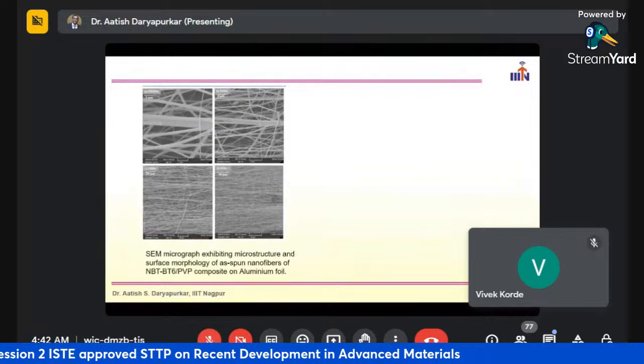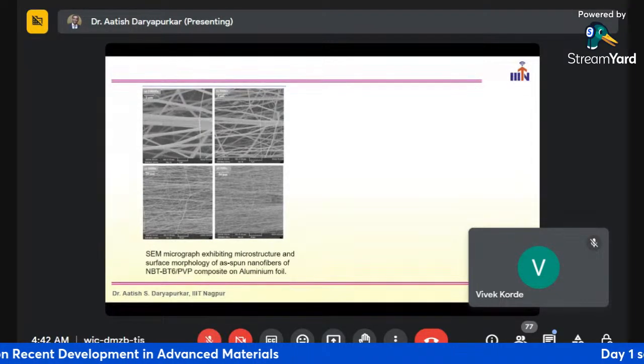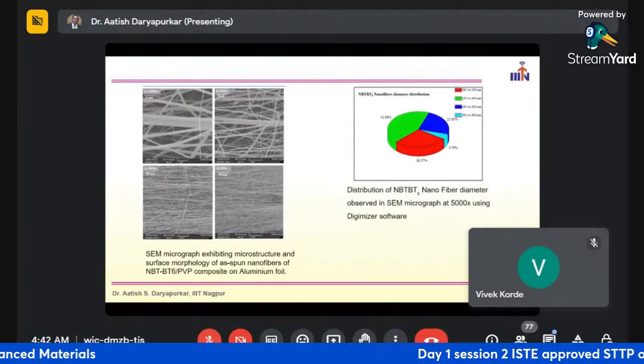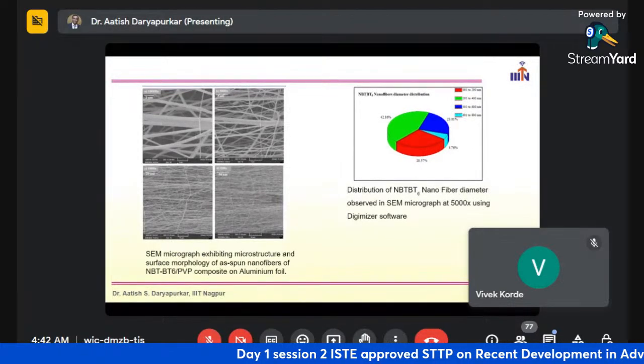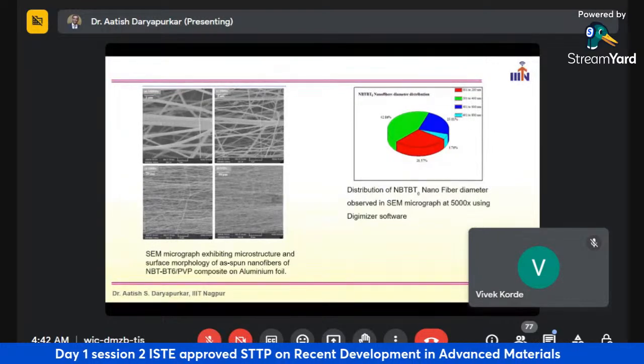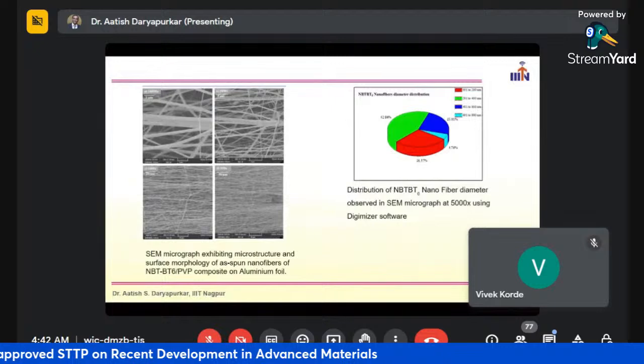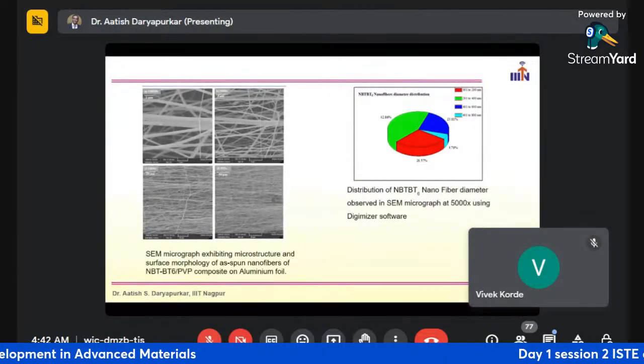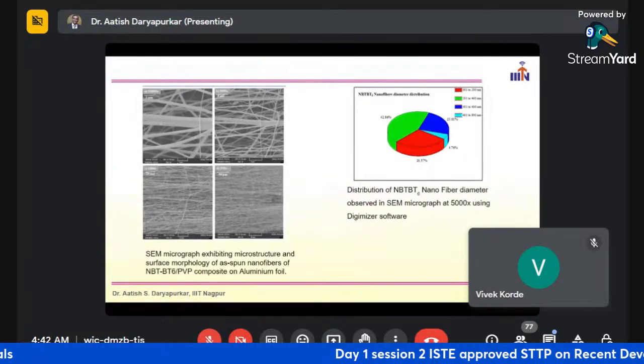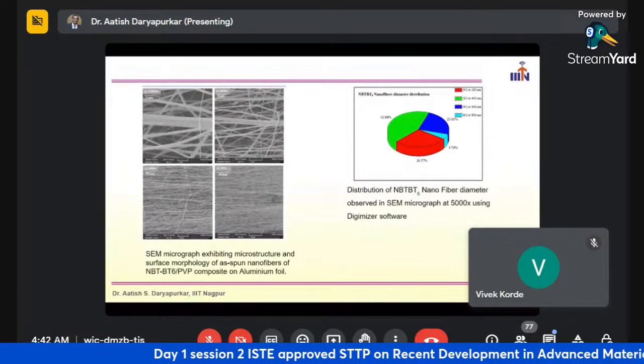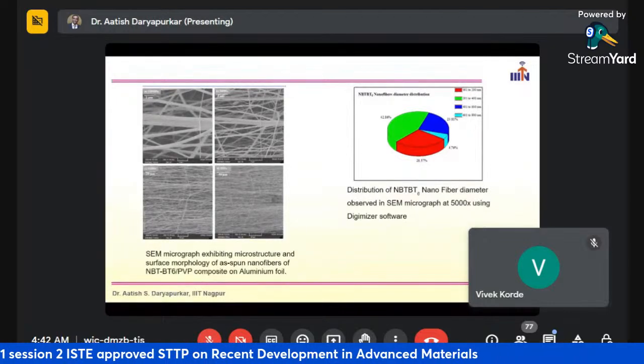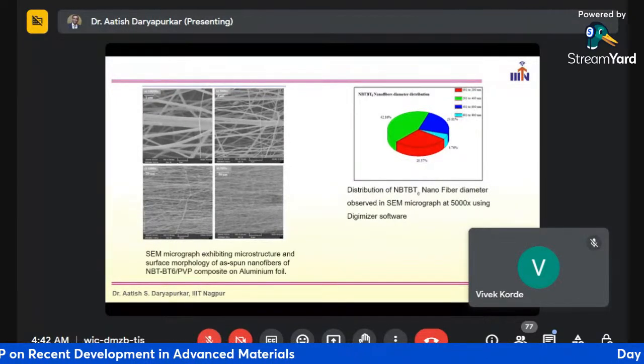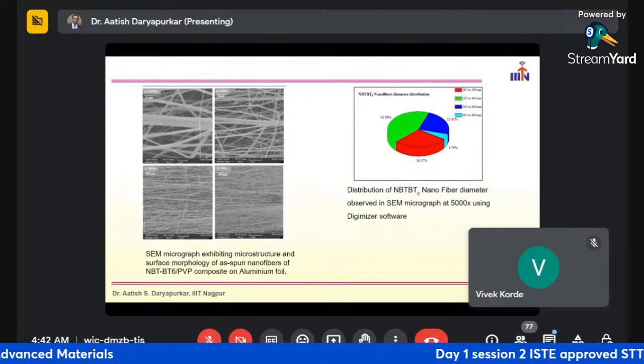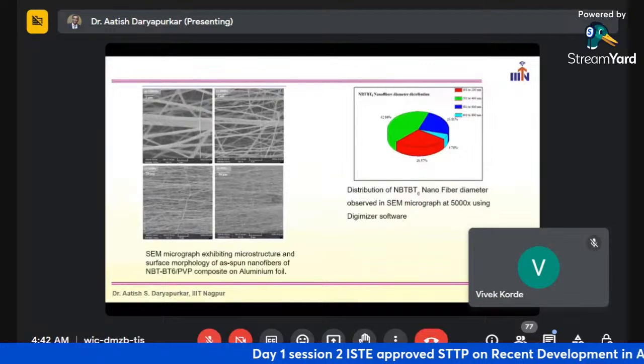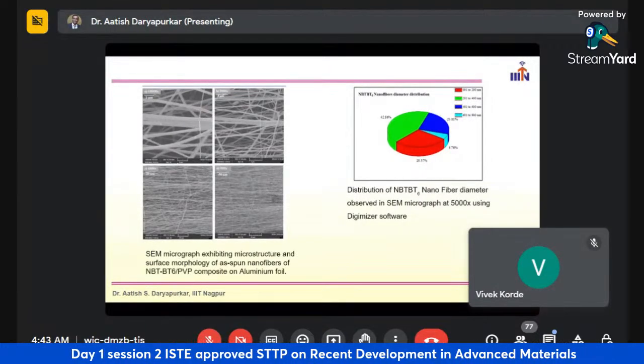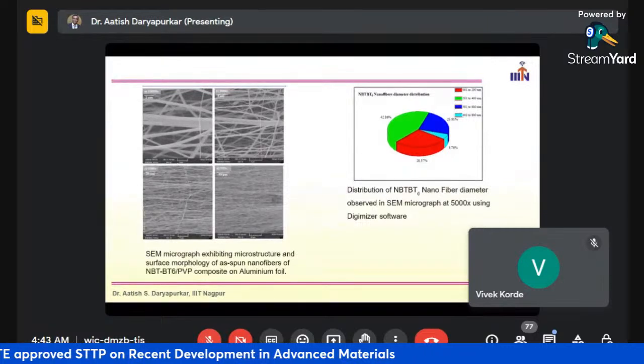On this slide, you can see the scanning electron micrograph of the fiber at different resolutions. Now this is the distribution of the nanofibers: how many there are and what the diameter is, right? If you see, in the 1 to 200 nanometer range, shown in red, 28.57% of the nanofibers are there. Then 42.86% of nanofibers are in the range of 200 to 400 nanometers, right? Then 400 to 600 nanometers, and then 600 to 800 nanometers. That is the diameter of the nanofiber. So the highest diameter of the nanofiber is 800 nanometers, and the minimum diameter of the fiber is 1 nanometer.